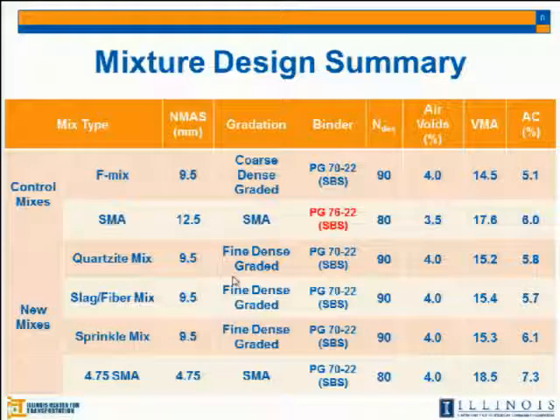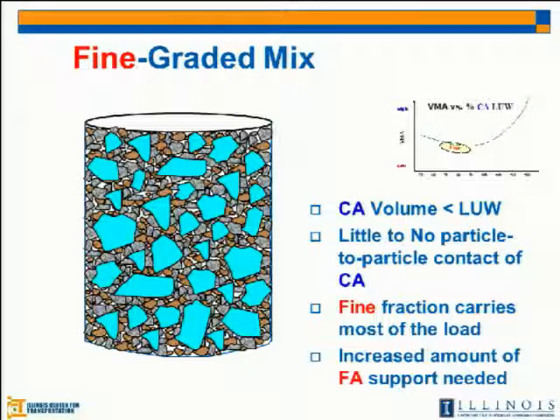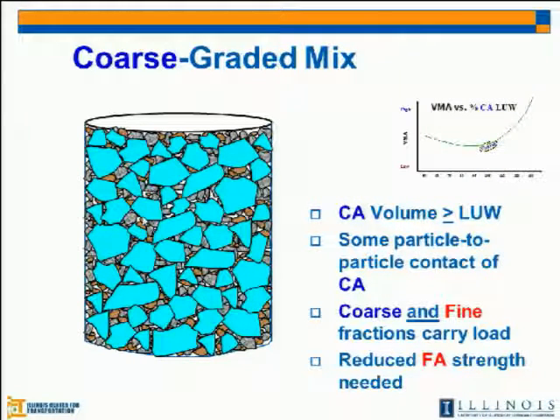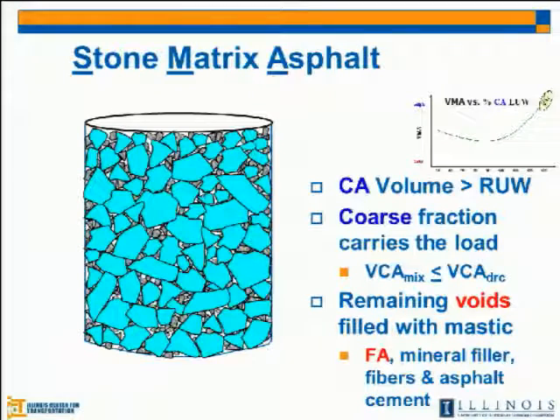We used the Bailey method to design this aggregate gradation. The big difference between coarse dense grade and fine dense grade is the aggregate structure. For fine dense grade, I will show you one. Yeah, here is fine dense grade. You can see the coarse aggregate is floating in the mixture. But here is the coarse dense graded mixture. You can see the contact of the coarse aggregate. But this is the SMA mixture.